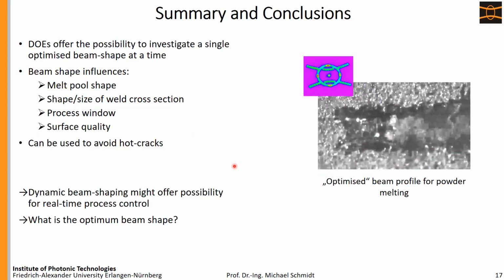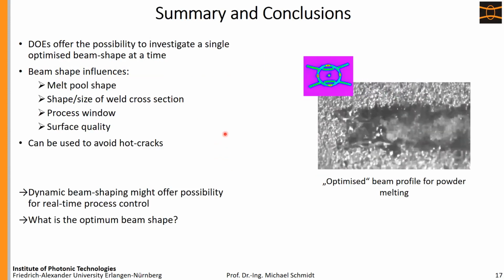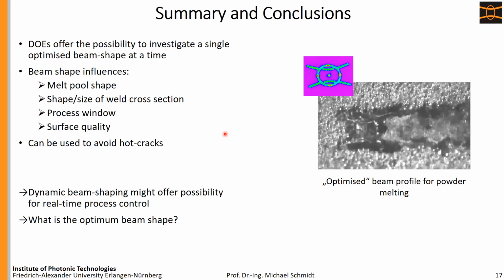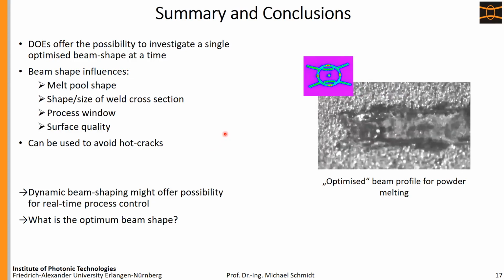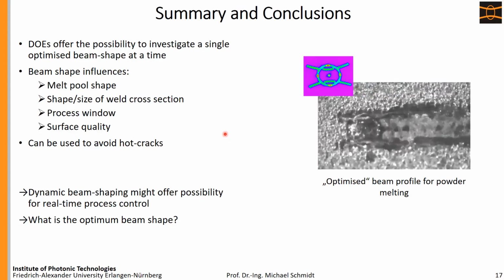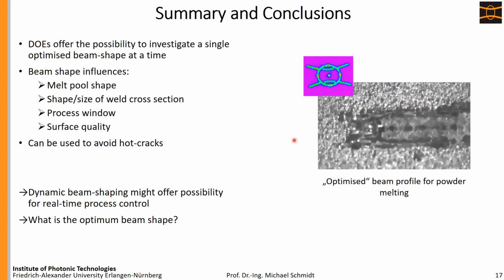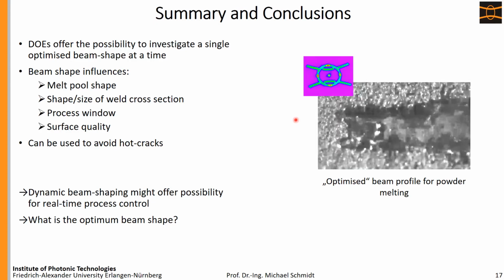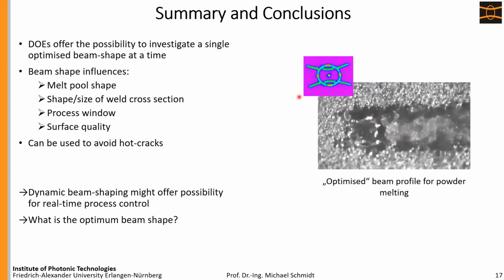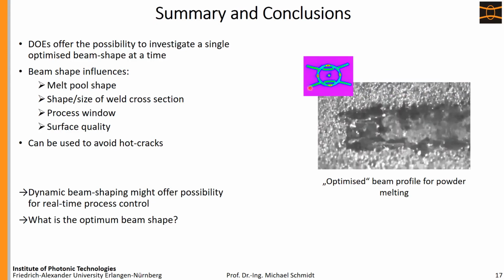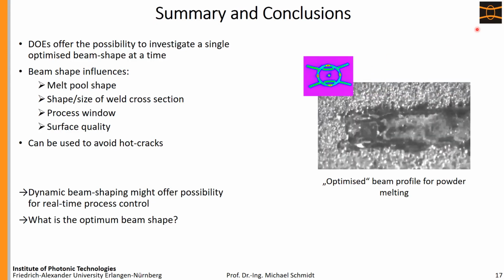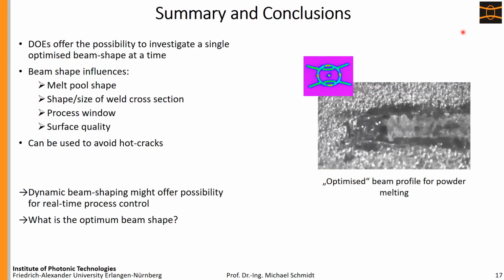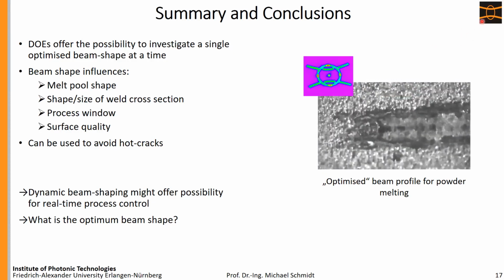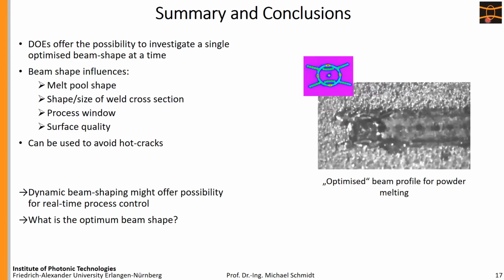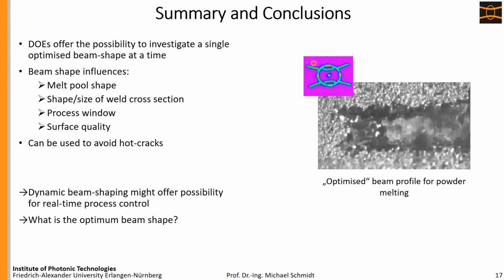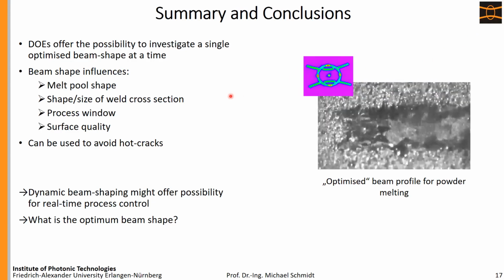Let me summarize what I just said. The DOEs, in general, offer the possibility to investigate just a single optimized beam shape at a time, but this already shows some good behavior. On the right side, you see one example done with what I'd call an optimized beam profile for powder melting. It's not only a ring shape, but a ring shape with two structures here. Interestingly, this is also the logo of my institute. We didn't know that before, because when we invented that logo, it was more like a bead in near field, or a bead trapped in a focus. Anyway, this seems quite good for additive manufacturing as well.